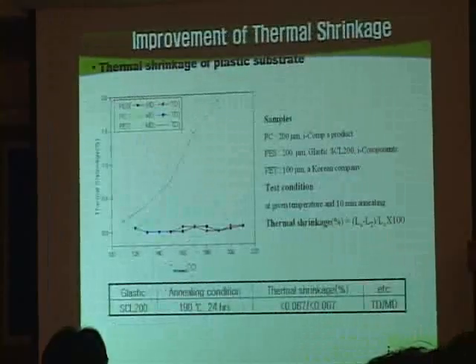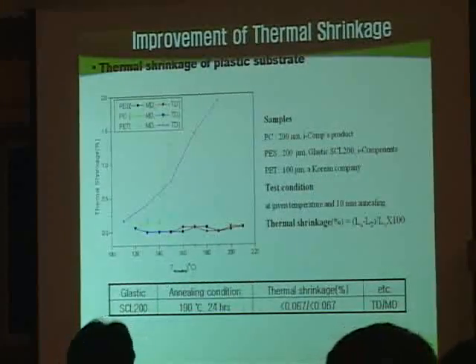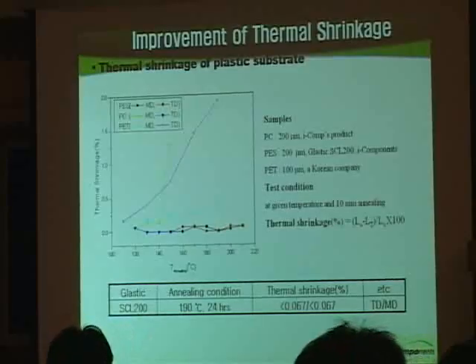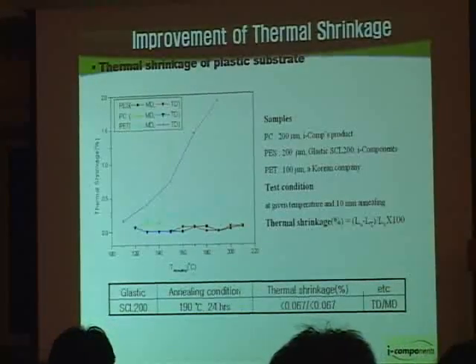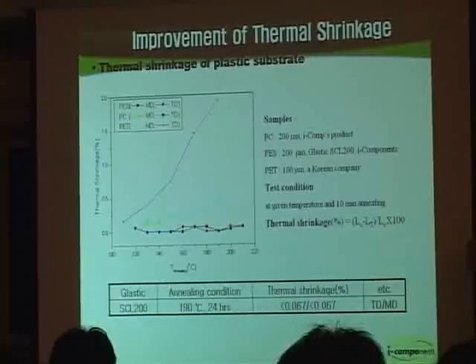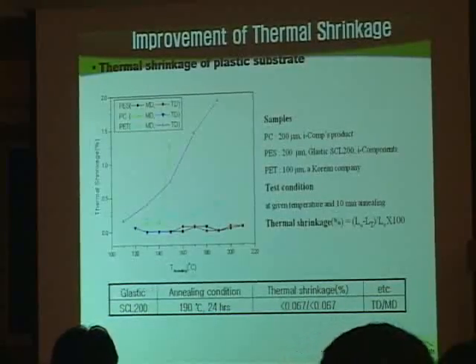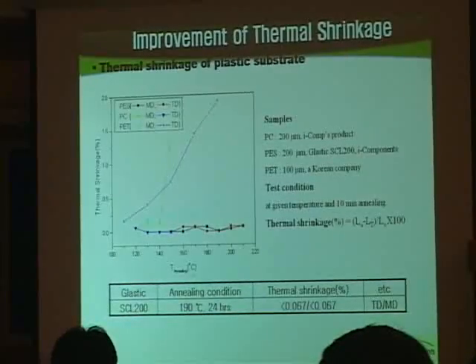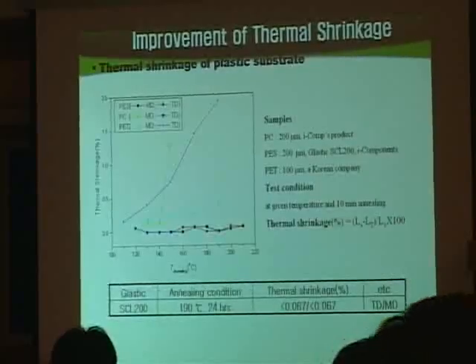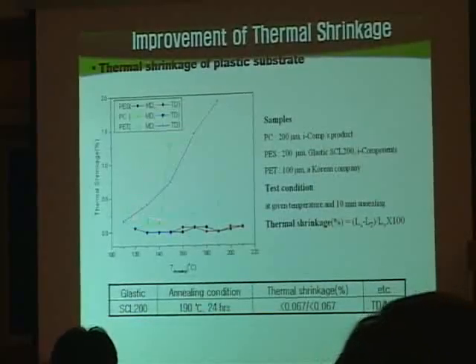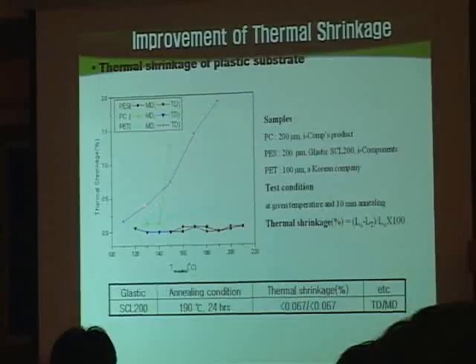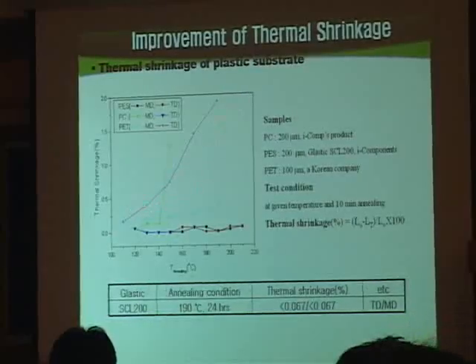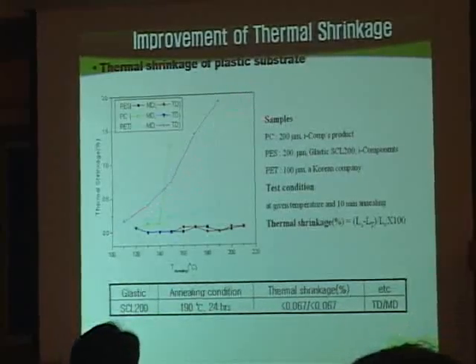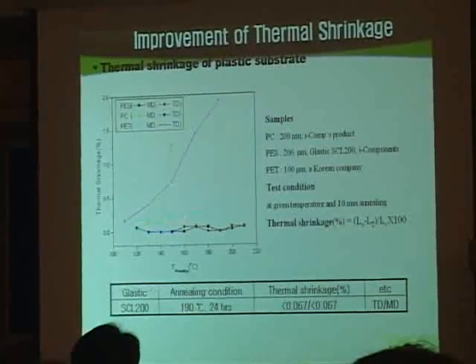One other thing we are very much concerned about is thermal shrinkage issues. I mean, we make the film, we make a substrate, then the problem is during or before utilization of this substrate, in the display process, there is always an issue of thermal shrinkage. For example, in PET cases, you have a lot of big shrinkage in the transport direction. And the other direction is rather okay.